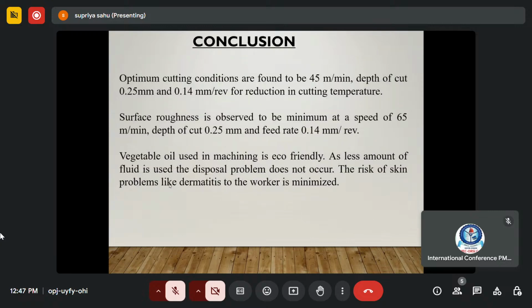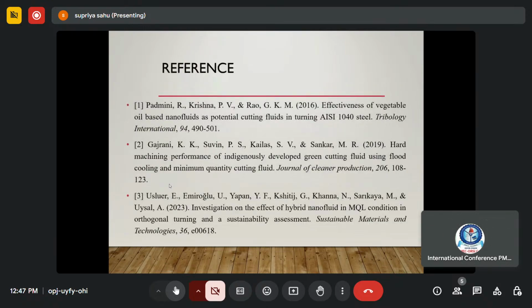So here is the conclusion. Optimum cutting conditions are found to be 45 meters per minute, depth of cut 0.25 mm and 0.14 mm per revolution for reduction in cutting temperature. The surface roughness is found to be minimum at 65 meters per minute, depth of cut 0.25 mm and feed rate of 0.14 mm per revolution. Vegetable oil used in machining is eco-friendly as a smaller amount of fluid is used. The disposal problem does not occur. The risk of skin problems is minimized.